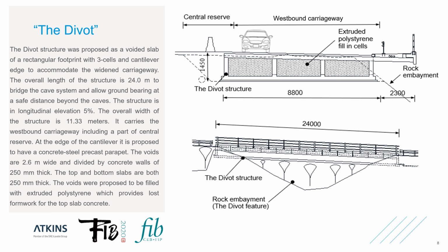At the edge of the cantilever, it is proposed to have a concrete-steel precast parapet. The voids are 2.6 meters wide and divided by concrete walls 250 mm thick. The top and bottom slabs are both 250 mm thick as well. The voids were proposed to be filled with extruded polystyrene, which provides lost formwork for the top slab concrete.